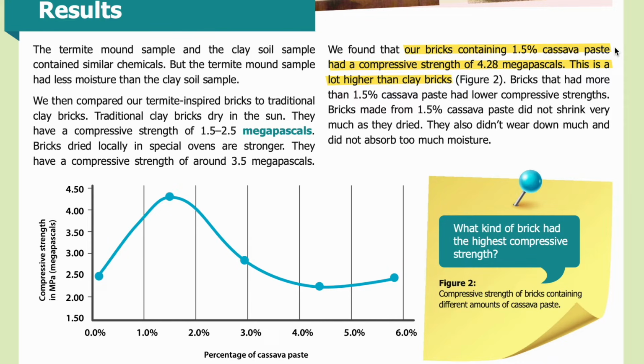We found that our bricks containing 1.5% cassava paste had a compressive strength of 4.28 megapascals. This is a lot higher than clay bricks. Bricks that had more than 1.5% cassava paste had lower compressive strength. Bricks made from 1.5% cassava paste did not shrink very much as they dried. They also didn't wear down much and did not absorb too much moisture.